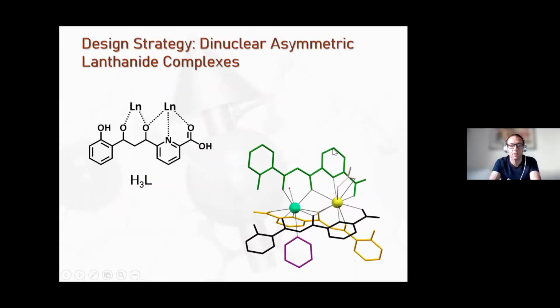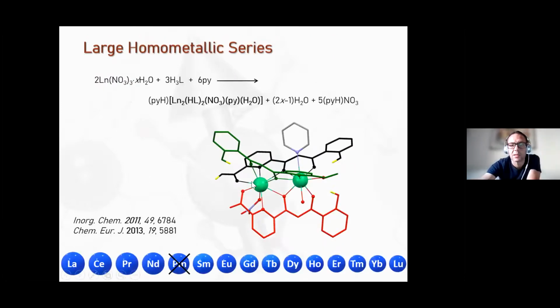So chemically, we can think about a way of putting 2 lanthanide metals together using ligands that are asymmetric, like this ligand here we made in our lab some years ago, that has 2 types of coordination pockets. And so by linking 2 lanthanide ions with 3 of such ligands, we unequivocally put 2 lanthanide ions in 2 different coordination environments, and therefore fulfill the asymmetry condition. And so we should make sure that this is a bridge that ensures an appropriate magnetic exchange so as to generate this 6 qubit system within one molecule that I mentioned. So I used this system to make the whole series of coordination compounds of lanthanides for the entire period, and we've been able to obtain the crystal structure of all of them. We've been studying these systems over the years.